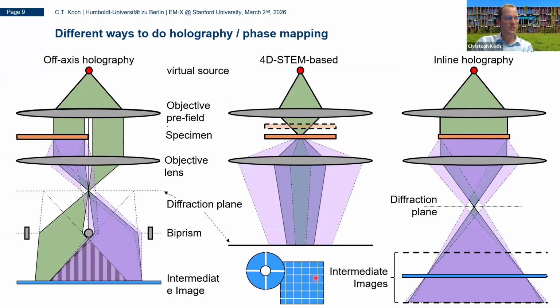Going back to Dennis Gabor in 1948, when he invented this principle of holography, pretty soon after with lasers, this off-axis scheme was developed. And then also when the field emission source for electrons was developed, there was then the Möllenstedt biprism, which allowed a reference wave going through vacuum and the object wave going through the object to be interfered, producing this interference pattern, which you can then interpret, for example, on an optical bench where you can do Fourier transformation and back Fourier transformation, so Fourier filtering, or in the computer nowadays.